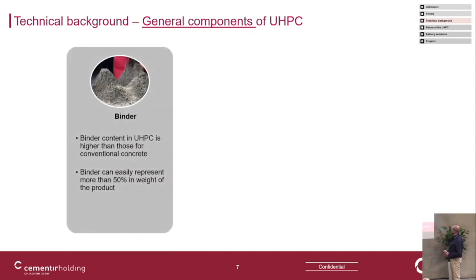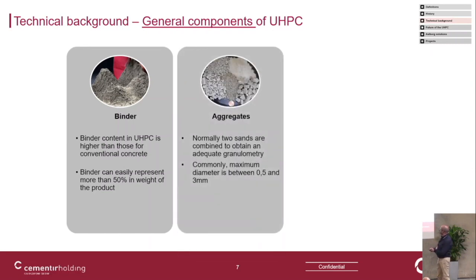If we take a closer look at the composition of these premixes, we have, of course, first the binder. In this kind of mix design, you need a really high content of binder, and that can represent more than 50% in weight of the product. Then you have the aggregates, or the sand fractions that we use, with a maximum diameter between 0.5 and 3 millimeters.